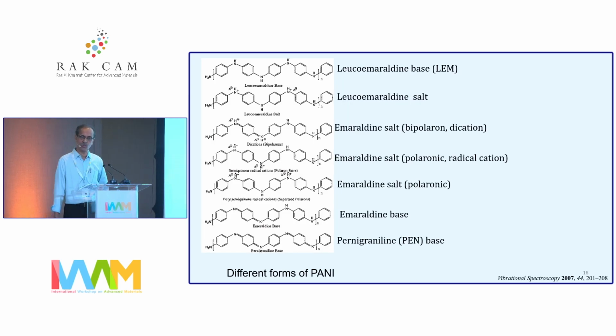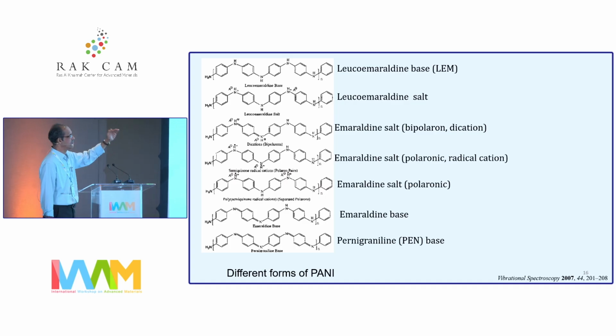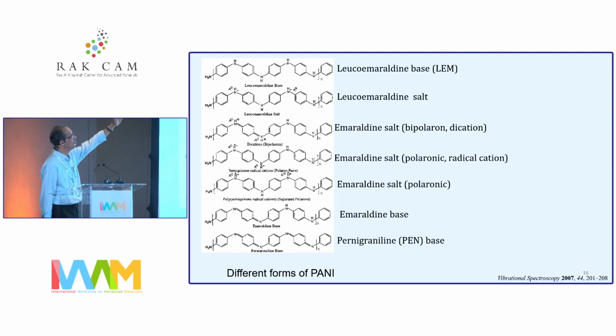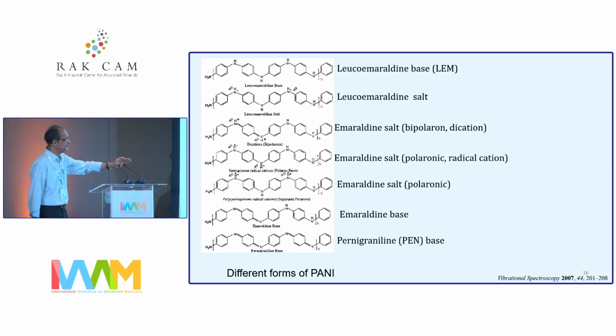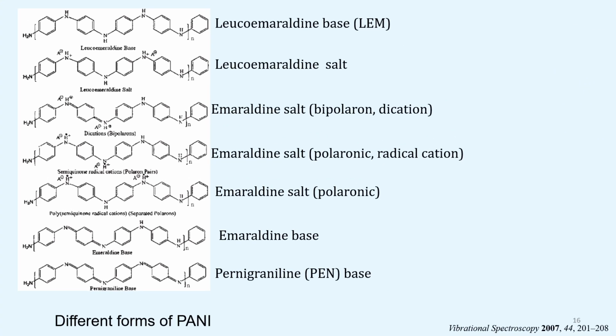Why am I talking about this particular example? Polyaniline reactions are quite well known in the literature. One understands all these stages of polaronic, bipolaronic form, the leucoemeraldine to pernigraniline, things like that. But what's of interest is the polaronic and the bipolaronic structure, wherein the polaronic structure has only benzenoid rings, while the bipolaronic structure has benzenoid and quinoid rings. And they do have different conductivity and different solubility. There's been lots of interest in the possibility of forming only the polaronic structure, for example.